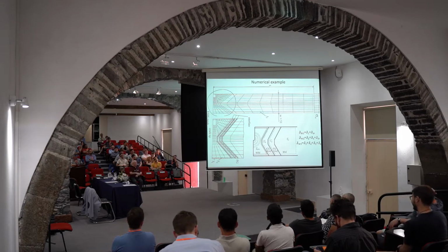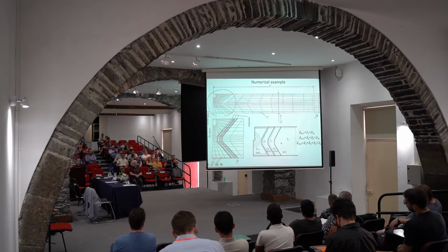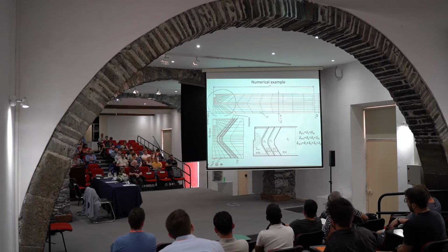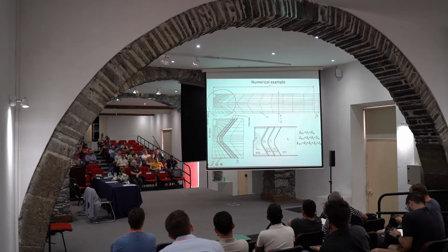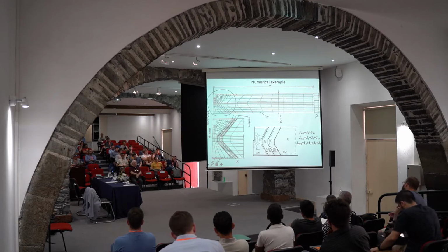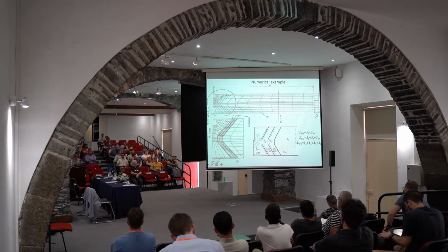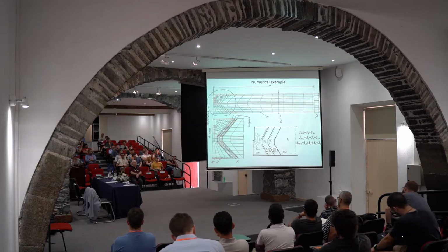So here we made this calculation, and of course, according to the previously shown slide, we can combine these integrals along paths which encompass the crack tip, like this one, and those line integrals which will actually show us how big is the contribution of the interface, how big is the error that we make if we neglect it.